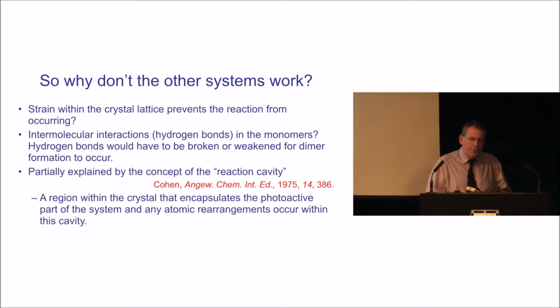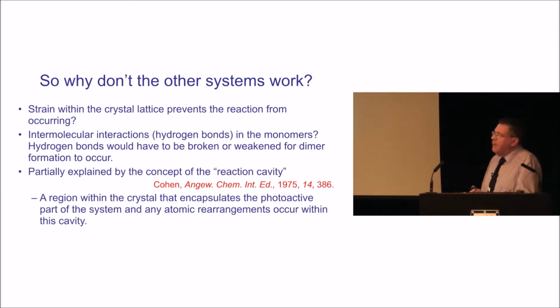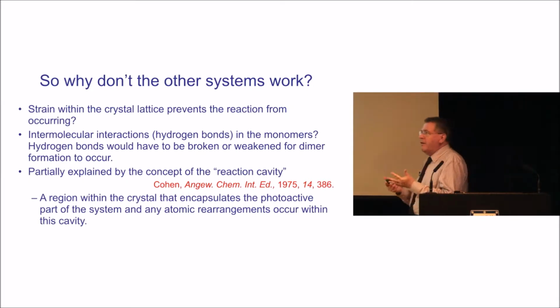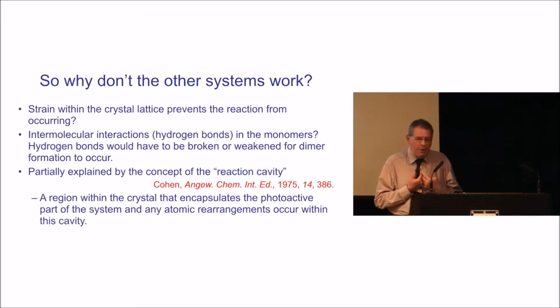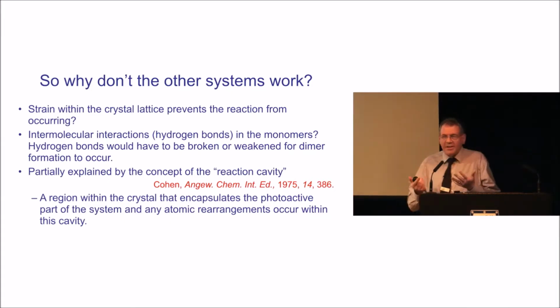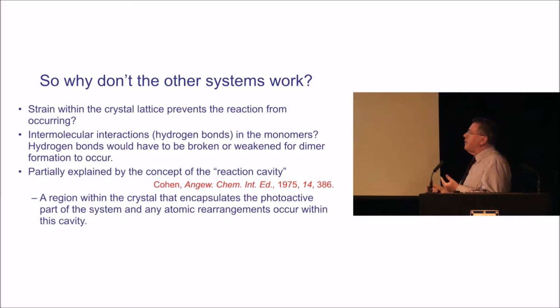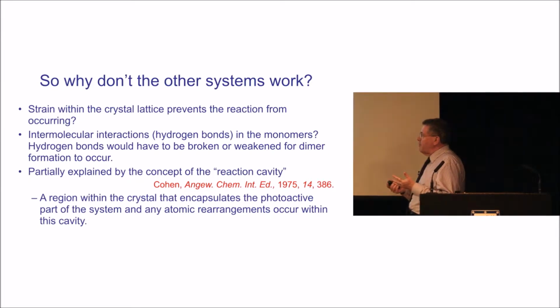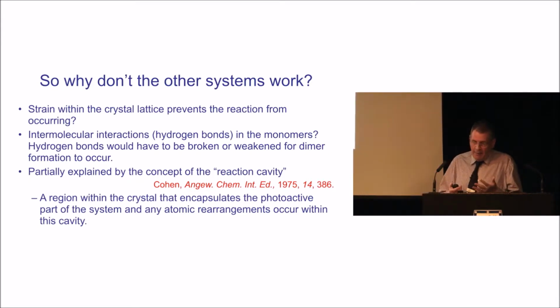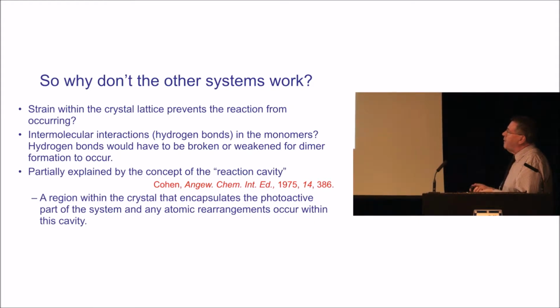Why didn't the other 3 go? Well, there is always this argument, it's crystal strain. The geometry change would be too big to allow the crystallinity to be retained. What does that actually mean? Well, it actually means something about intermolecular interactions in the monomer starting material being too strong, perhaps, and you need to get over too much of an energy barrier for the process to occur.